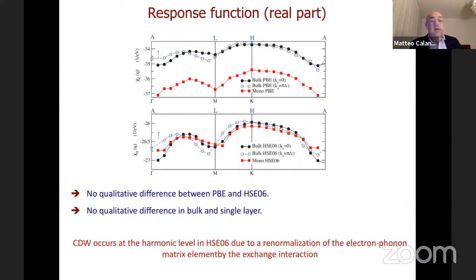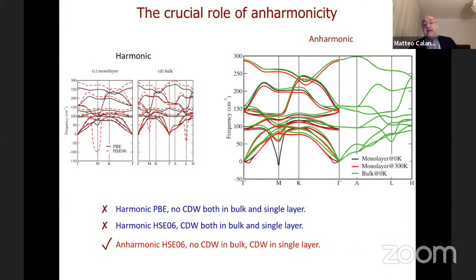Now, we have explained how the harmonic calculation works, but we still have the problem that the harmonic calculation is finding a charge density wave instability both in bulk and in single layer, while in experiment there is not. So what is the key, the missing ingredient? Let me remember the situation at the harmonic level: an unstable phonon both in bulk and in monolayer. The ingredient that is missing is actually anharmonicity. As you can see, anharmonicity that of course we did only on a very small supercell, 4x4, because HSE06 was too expensive.